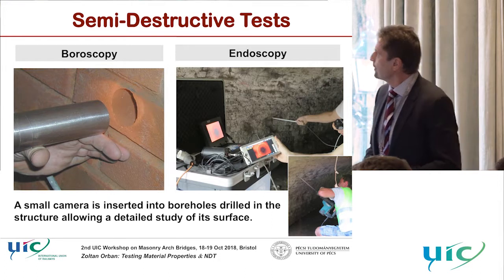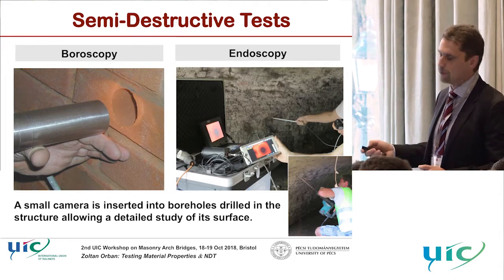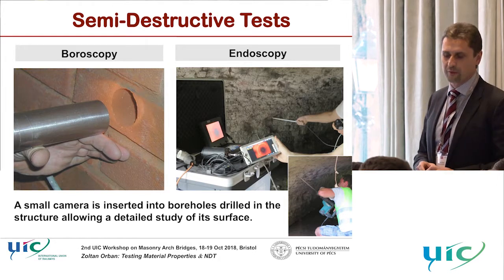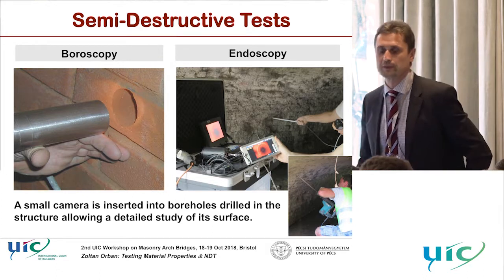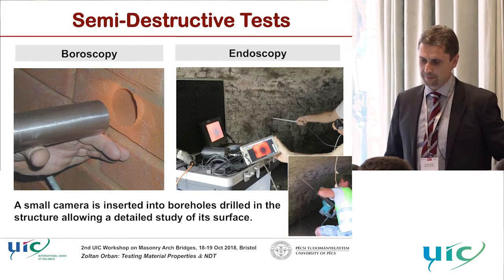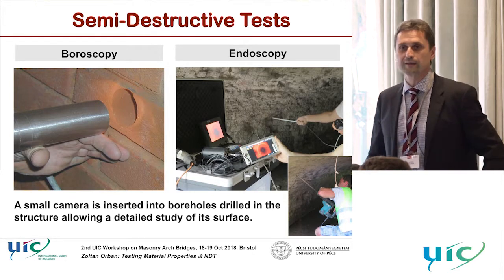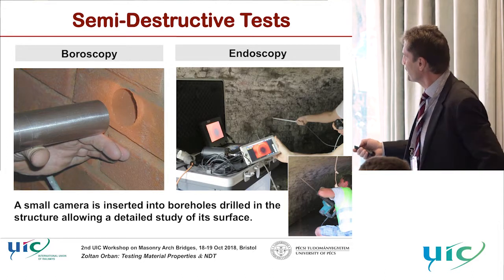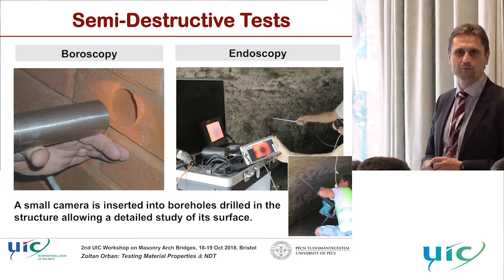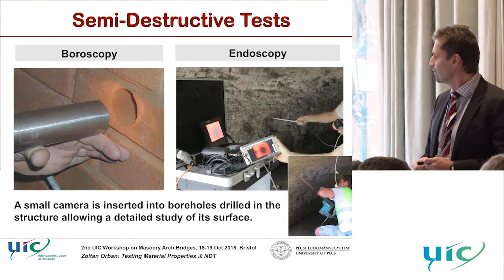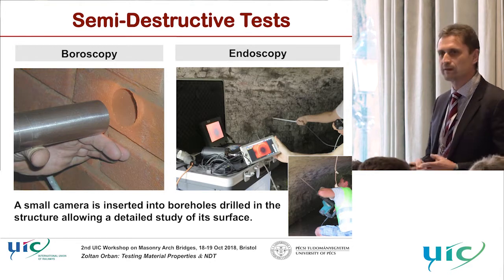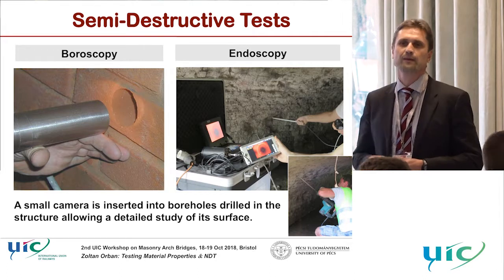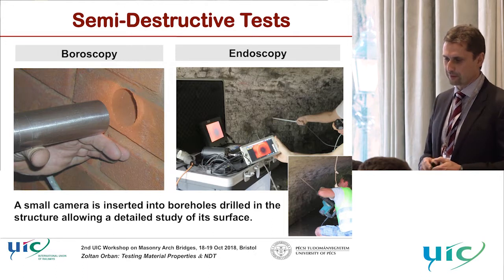I would like to mention boroscopy or endoscopy as some of the most effective tools for analyzing masonry structures. A small camera is inserted into boreholes drilled in the structure, allowing detailed study of the surface. Drilling resistance itself gives very reliable information on condition — if something changes during drilling, it indicates a change in conditions. If you can also measure torque accurately, it can give even more accurate results.